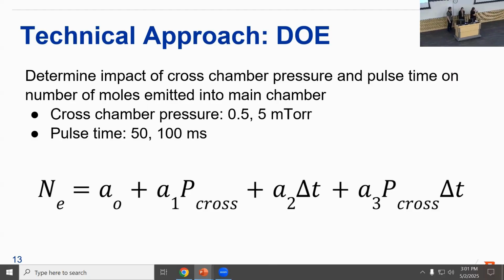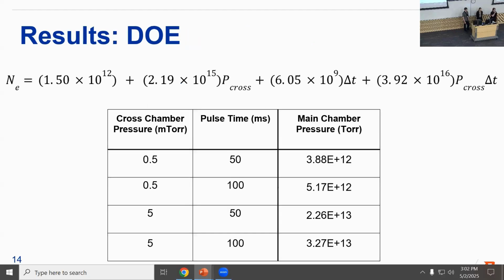So in this general equation that is generated from the DOE matrix, NE is the number of molecules emitted, A0 through A3 are the effects that are calculated from that matrix, P cross is the cross chamber pressure, and delta T is the pulse time. And as for the results from the DOE, as you can see from the generated equation, the cross chamber pressure has an impact 6 orders of magnitude greater than the pulse time. And we will get into that more later.